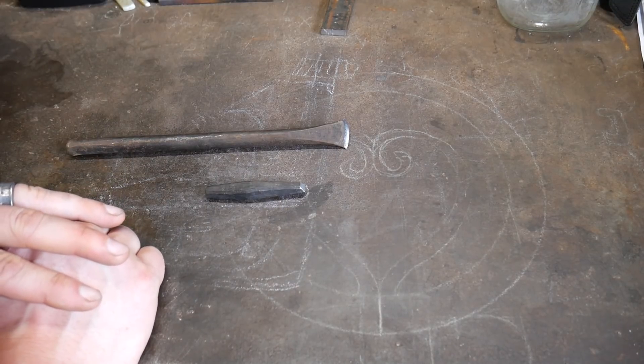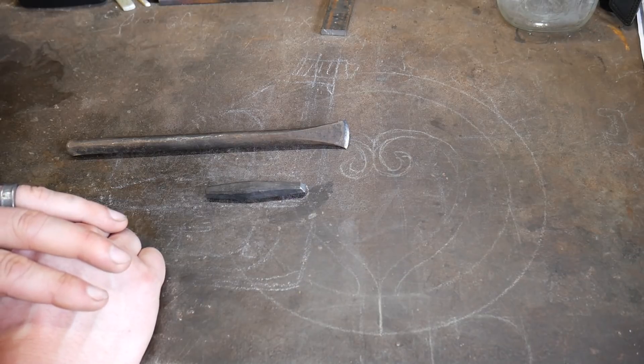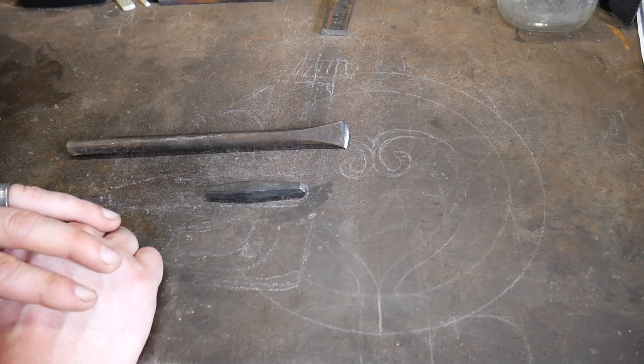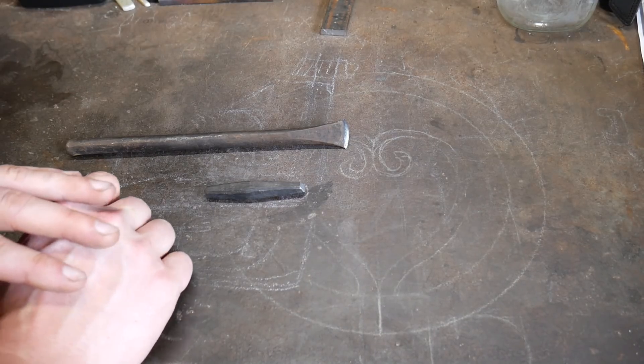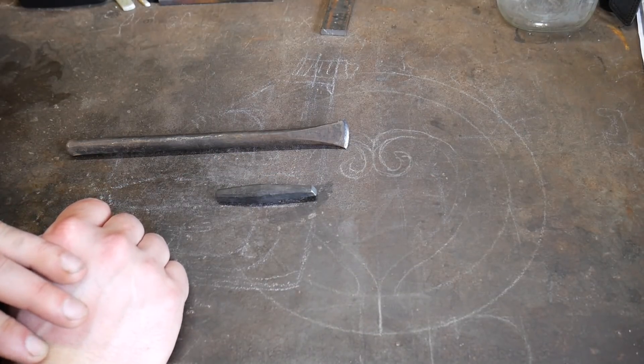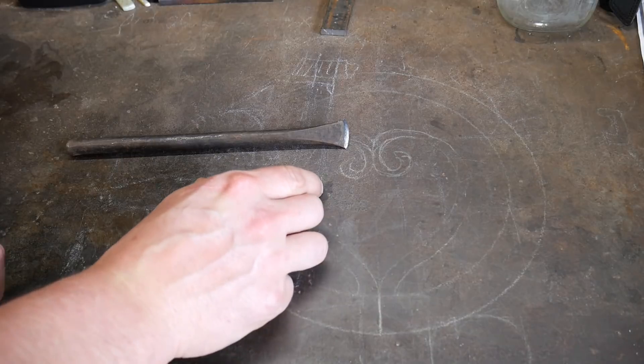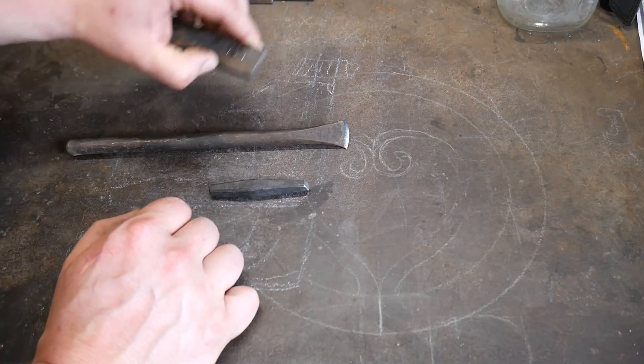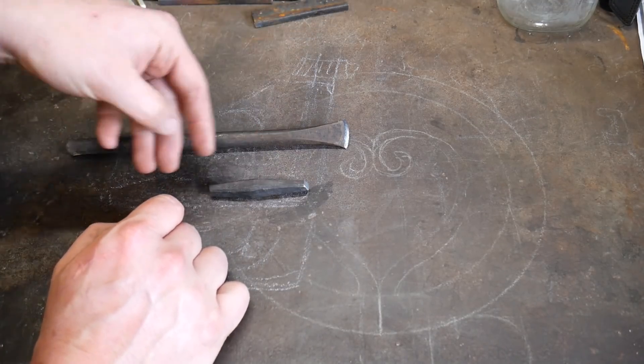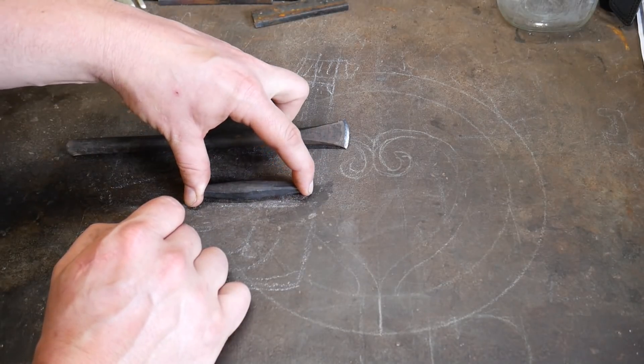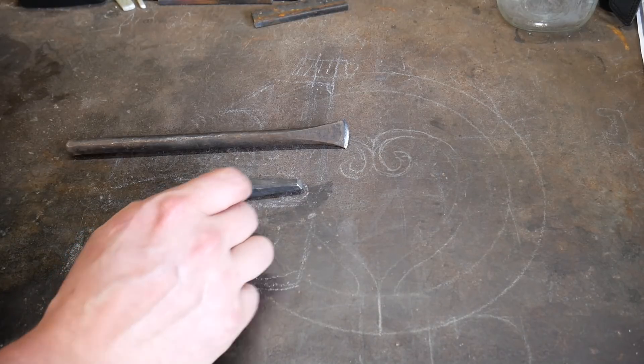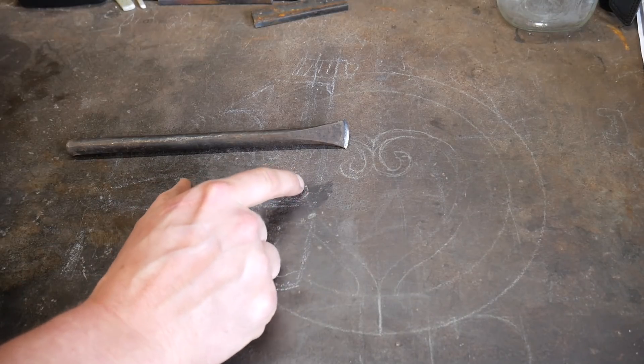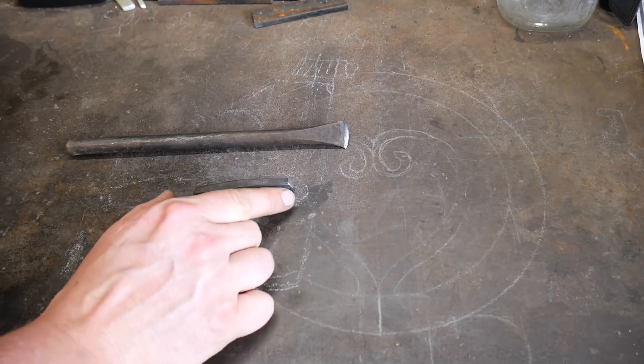Even simple carbon steels and spring steels have been hardened in water. I needed a water quench on this tool because I'm going to be engaging other tool steels and hardened steels while cold, doing chasing. This needs to be as hard as possible to retain its edge. This will get drawn back to a very light straw color, and if I fear it has more stress or will take more stress, I'll draw it back to a bronze color.